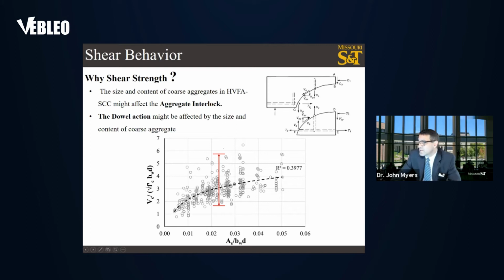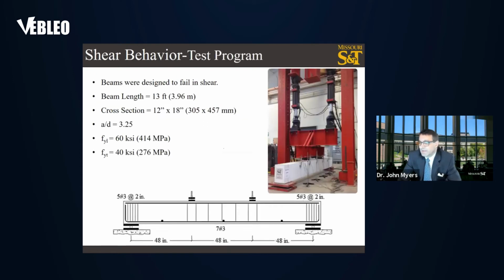So one of the concerns about shear strength and self-consolidating concrete is the behavior of aggregate interlock. Aggregate interlock allows additional shear capacity from the concrete based on the size and volume of coarse aggregate. Of course, in SCC, we use smaller aggregate and fewer coarse aggregate in the mix, raising the concerns about that along with dowel action. These are two of the critical components that contribute to shear strength in concrete.